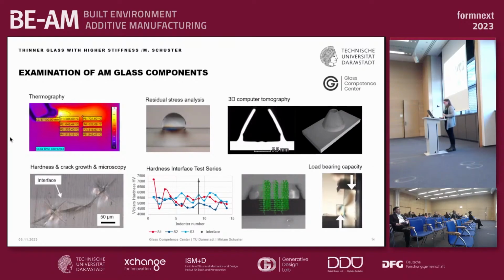We can also do some mechanical testing. For example, we can determine the hardness of our sample. So these are the three lower pictures beginning from the left, where we did some indentation tests on a printed wall, which was on a base plate. Here in this graph, we see the hardness on the y-axis, and on the x-axis, we see the position on our printed object, and the black line is the interface of the base plate and the printed wall. We can see that there is almost no difference in hardness, which is good, which means that we have almost constant material behavior.